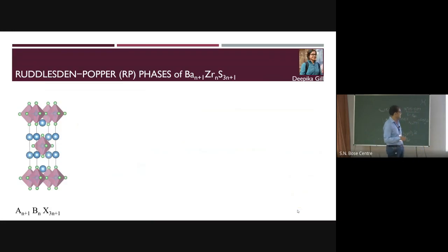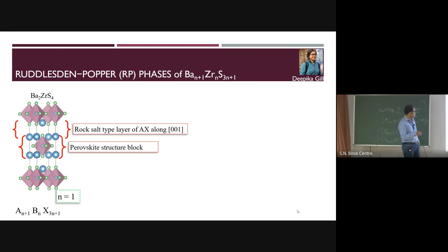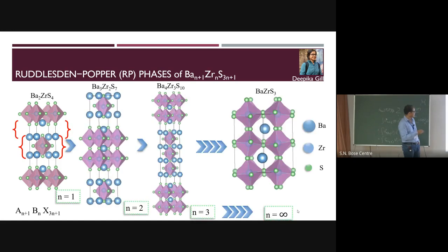That's why we went to two-dimensional perovskites, to see what is happening there, because once you have a 2D structure, the physics is very different and the expressions are different, and usually they should have better mobility and similar. So this is called the Ruddlesden-Popper phase. This is n equal to 1 because we have one layer. Now this is n equal to 2, you have 2 layers, then this is 3 layers, and this is n equal to infinity.